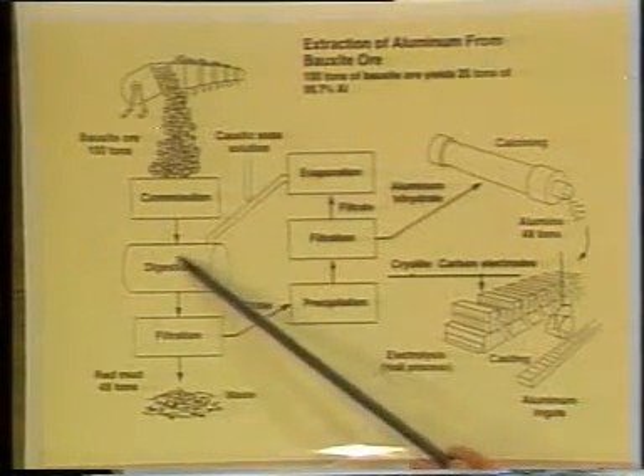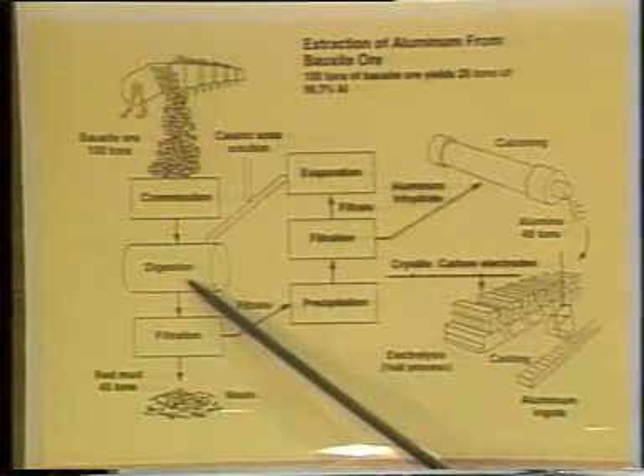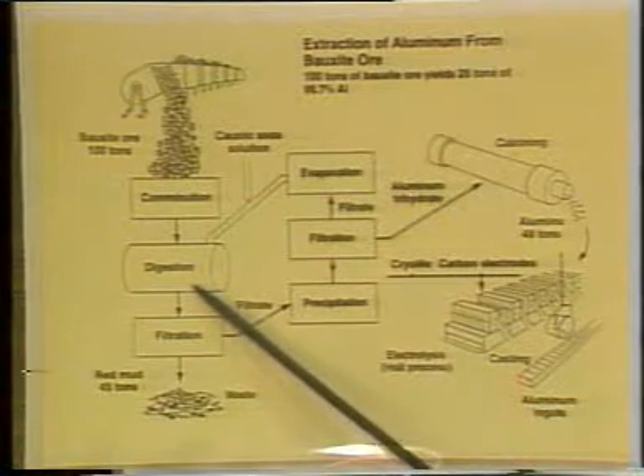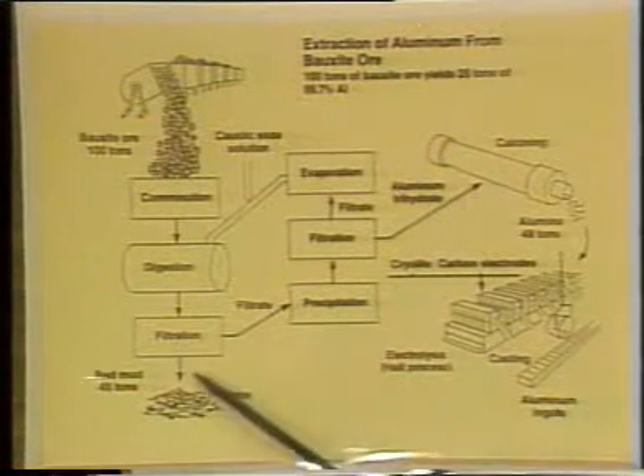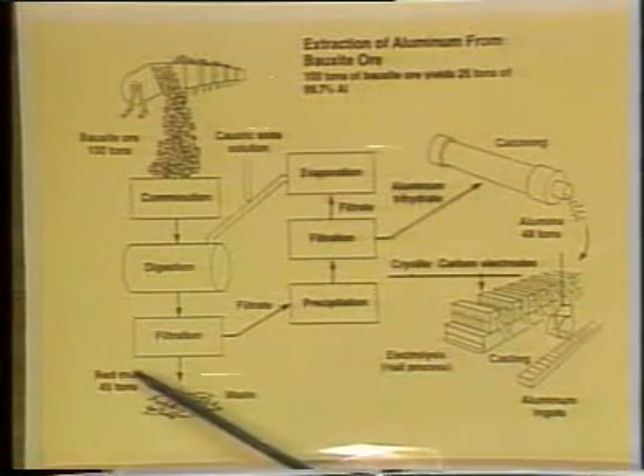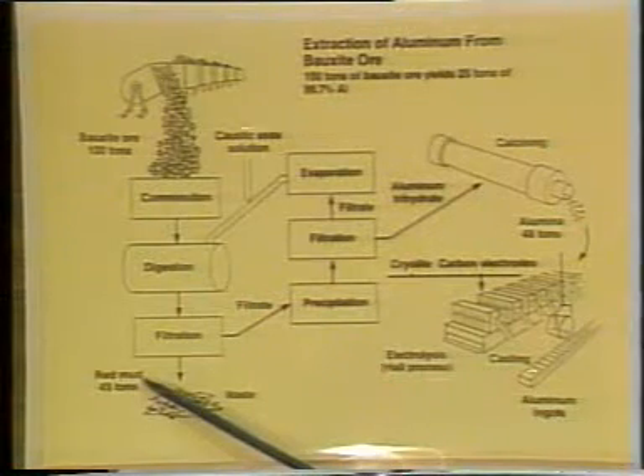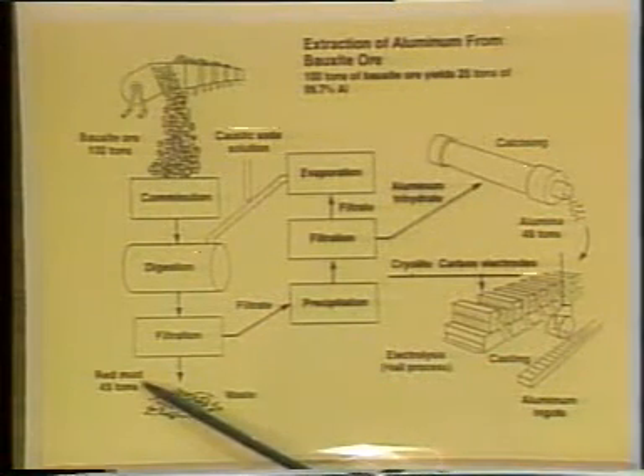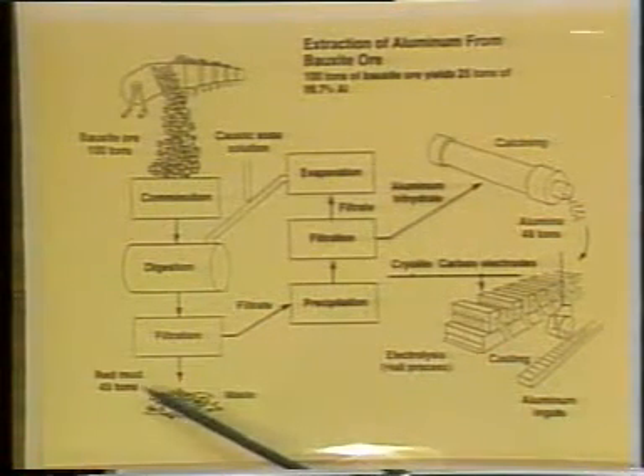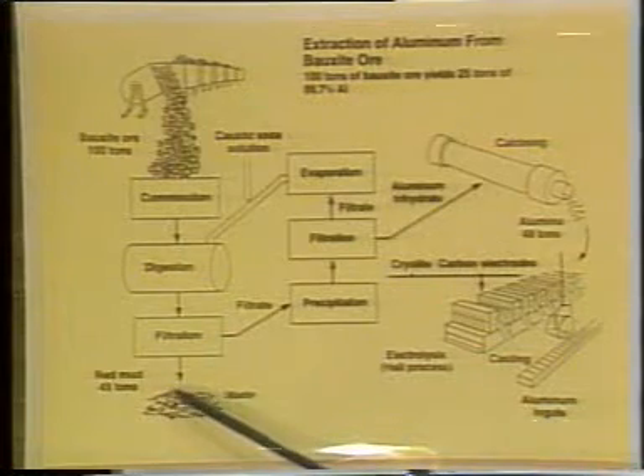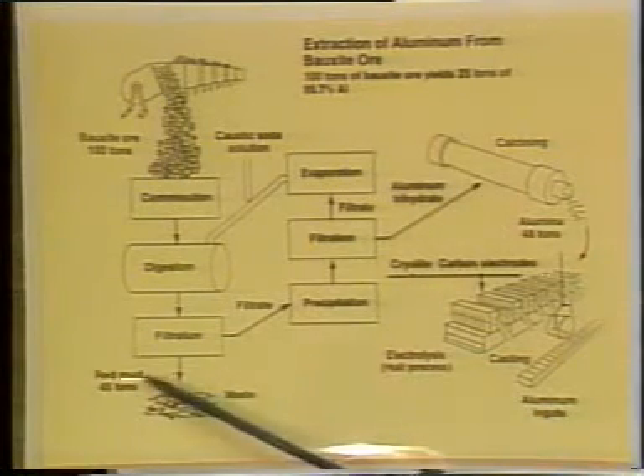And we take this caustic soda solution now, which is going to contain the alumina as a sodium aluminate, and we filter it. And what we filter out is a red mud. That red mud will contain almost all of the silica and all of the iron, or virtually all of the iron. Because these particular materials don't dissolve readily in the sodium hydroxide solution, at the concentrations we have.